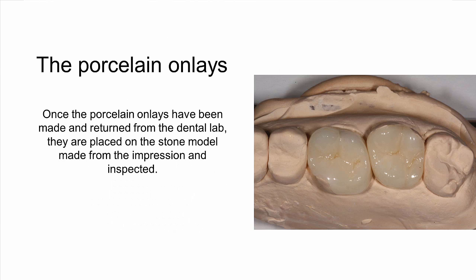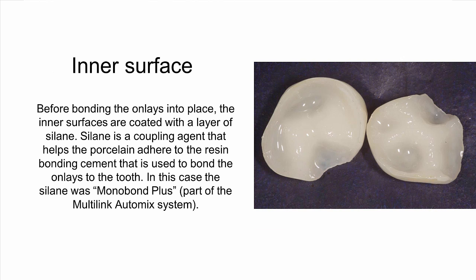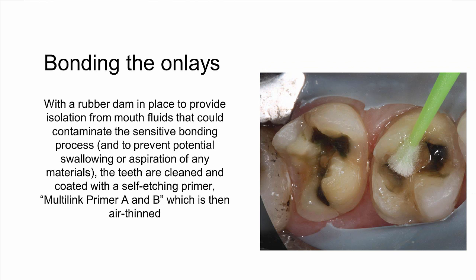So here you see a picture of the porcelain onlays that have been fabricated by the ceramist and returned from the lab. So we place them on the stone model and make sure that they fit properly, inspect them and check that everything looks the way it's supposed to. Then the inner surface of the porcelain onlays is coated with a layer of silane. Silane is a coupling agent that allows dissimilar materials to adhere to each other. So it aids with the porcelain adhering to the resin bonding cement that is used to bond the onlays onto the tooth. So in this case, the silane used was something called Monobond Plus, and it's part of Ivoclar's Multilink Automix system.